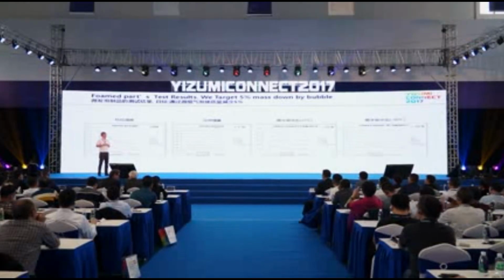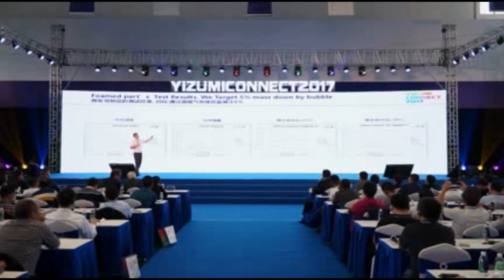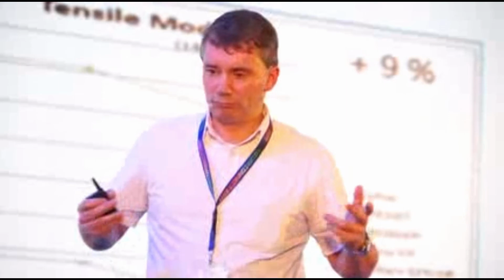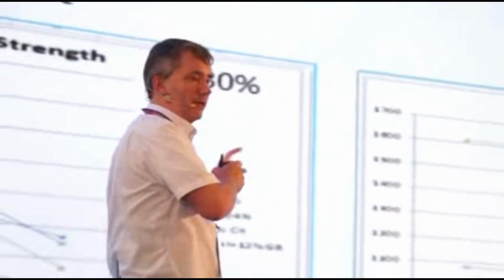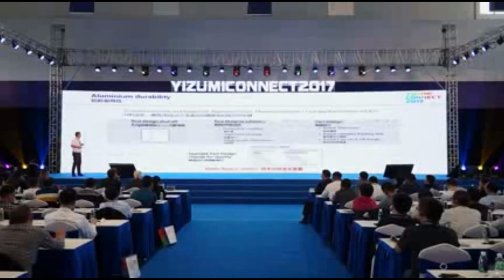Tensile modulus, the flexibility of the product, can be slightly higher. We're looking at impact at 23 degrees, a little bit lower, and the impact at minus 30, again, a little bit lower. But the key thing with the foaming technology is you have to change every way of thinking how you design the parts. Do you add more ribs? Do you add less ribs? There's a lot of know-how that goes into how we design to make sure that we can change these. This is the result from doing tests on just small plaques, standardized tests. The reality on a real product can be different, and we know this.